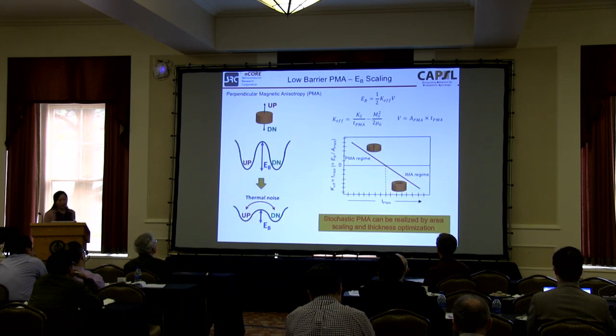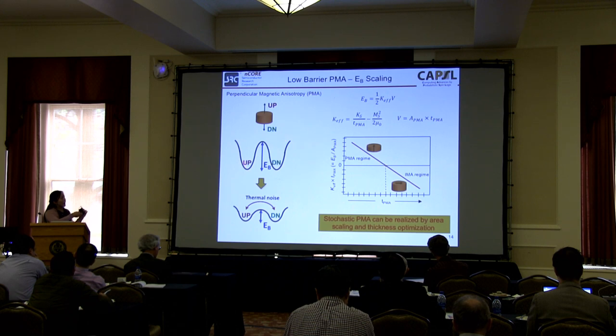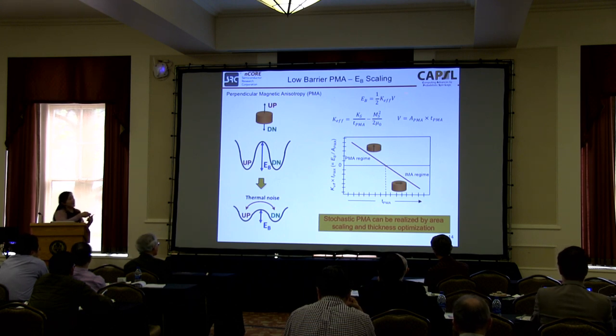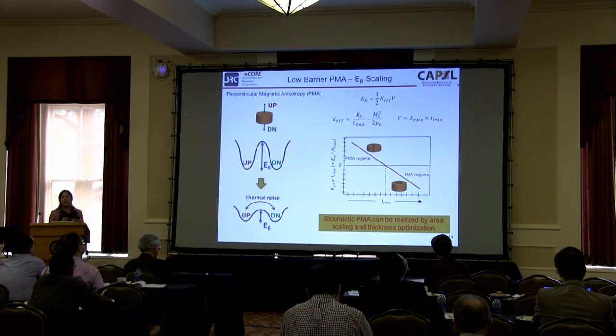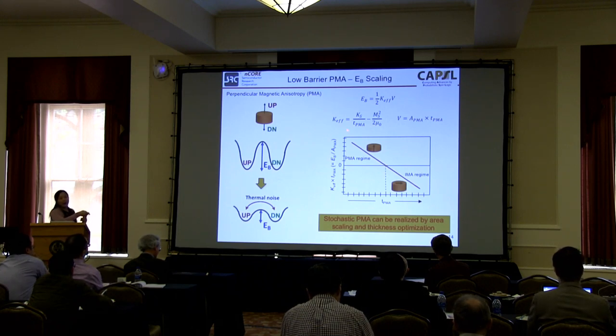And now let's talk about the PMA energy barrier scaling. We also have two methods. For PMA, these magnets have a perpendicular anisotropy, and normally it's out of plane. And we can also reduce the energy barrier now by not only scaling down the area, but also working on the thickness of the magnetic film. That is because the energy barrier is proportional to the volume and the anisotropy energy density. The energy density is described by the interfacial anisotropy energy and the demagnetization energy.